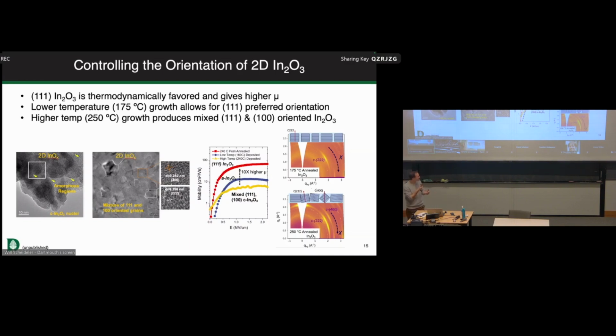So Sam's been developing this process. The idea essentially is that when you first deposit it, you have some nuclei that are already in that preferred orientation. They're interspersed in an amorphous indium oxide, and as you grow them, they start to essentially reach a fully crystalline state that can be highly ordered. And the advantage of that is that you can get better electronic mobility. So this parameter that really determines how good the circuits are that we can make, whether we can switch at high frequencies, all the characteristics that we might need as we go to the system level for thin film electronics.